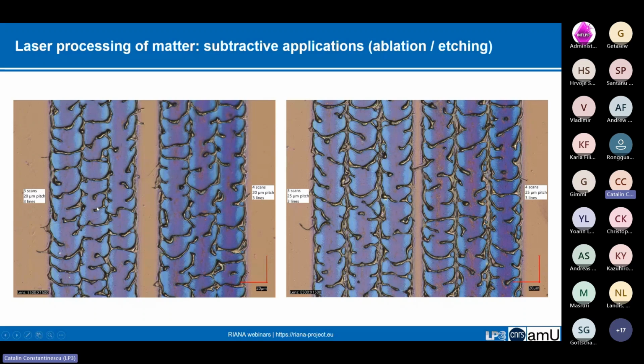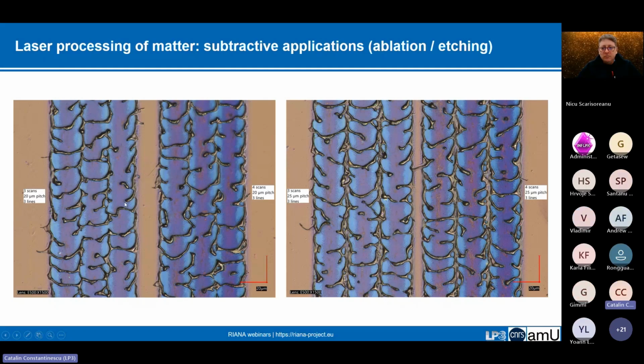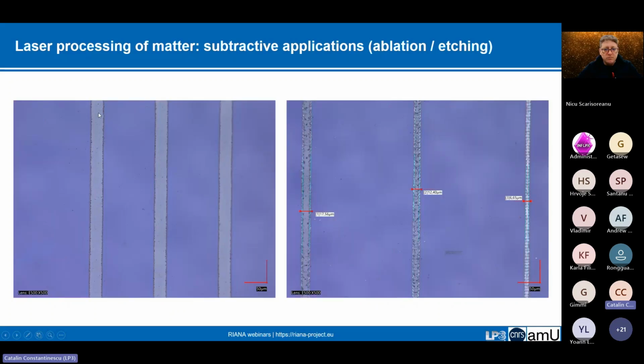So we scanned in femtosecond in order to ablate a structure which is in this case a multi-layer of 3 different thin films. And by changing the pulse duration, look, so here we have picosecond, which is for the moment something we need to further process to understand how this is taking place. These examples of ablation of subtractive case studies can be controlled in order to achieve nano and microstructuring across various materials, and therefore demonstrating their scalability and repeatability.